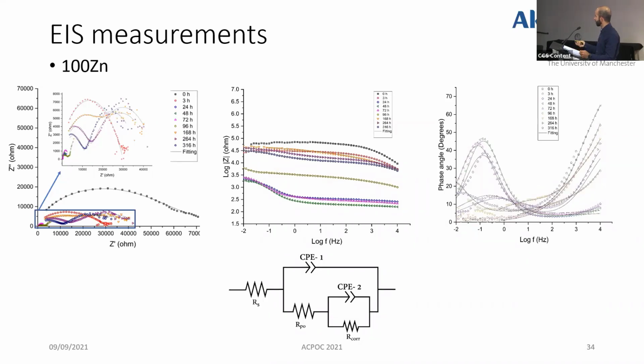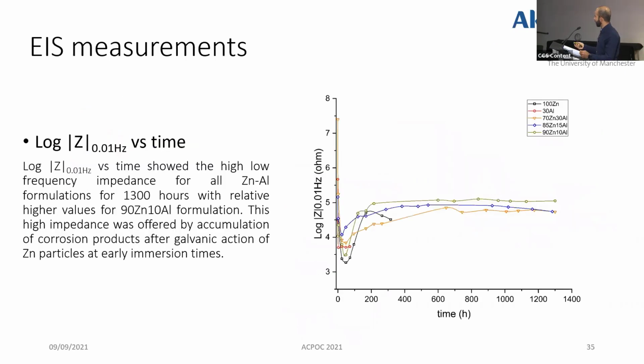So this is an example of EIS measurement for 100 zinc, the control coating. You can see that most of the measurements show 2 time constants, which are fitted with this circuit, the part with the coating and the other part for the metal at the higher frequency. To summarize the EIS measurement, I plotted the log impedance at 0.01 Hertz versus time. And as you can see here, there are relatively higher values of impedance for 10 to 15 volume percent of aluminum, which offer more protection. And up to this point, which is 1,300 hours, there is no sign of rust for these coatings in comparison with the control zinc or 30 aluminum coating.